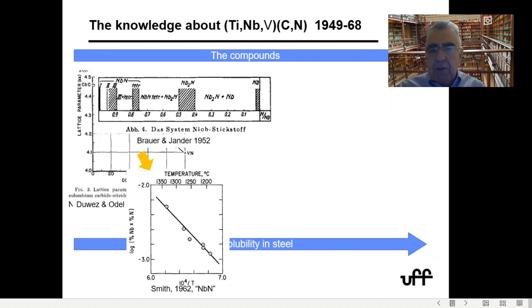Back then in the 60s, so 10 years after that, there was the first attempt at determining the solubility product of niobium nitride in steel, not niobium carbide. And this was done by Smith. And he measured the solubility of the nitride.